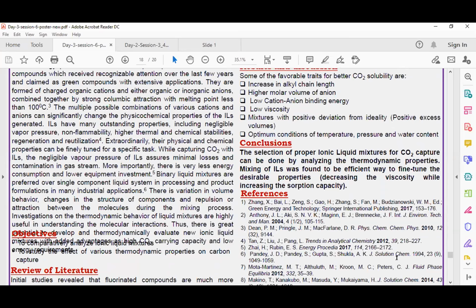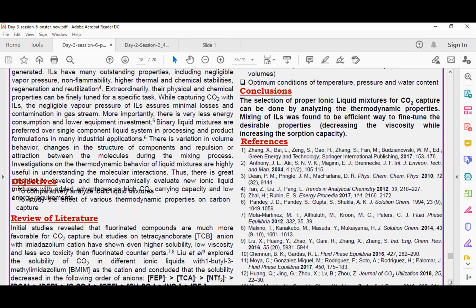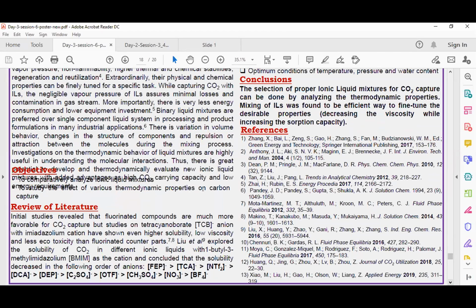The main objective of our study is to comparatively analyze the ionic liquid mixtures and to study the effect of various thermodynamic properties on the carbon capture. Initially, in some of the studies, we have found that the fluorinated compounds, the compounds which have fluorinated anions, are favored for carbon capture. But then we have studies where the tetracyanoborate anion was favored with the imidazolium cation. Imidazolium is one of the basic cations that is used in ionic liquids. Also, with the tetracyanoborate anion, we have higher solubility, low viscosity, and less ecotoxicity. Then there were further studies where the anions were compared for their carbon capture. According to these studies, tris(pentafluoroethyl)trifluorophosphate was found to have the highest value as an anion for carbon capture.